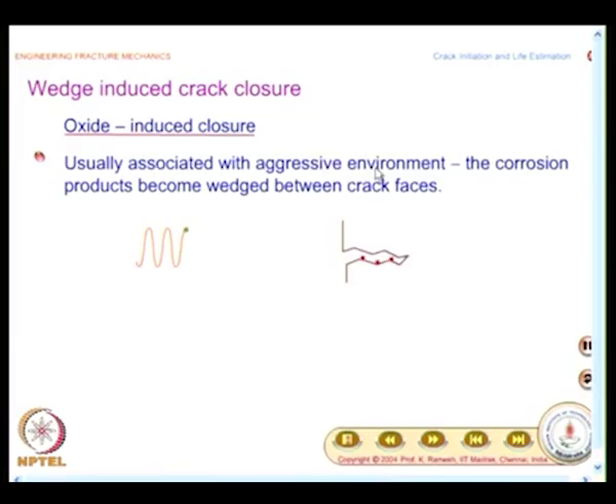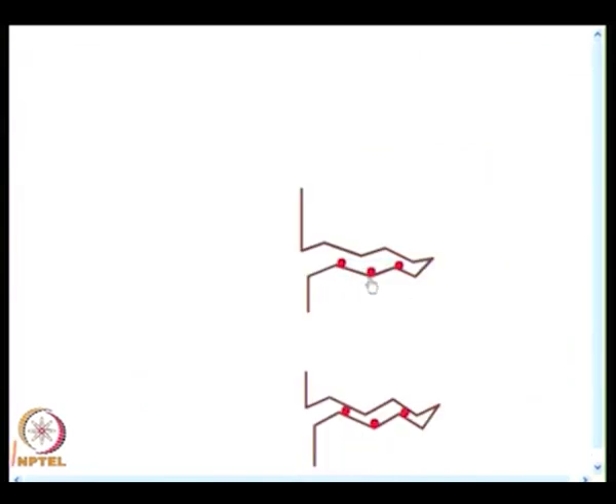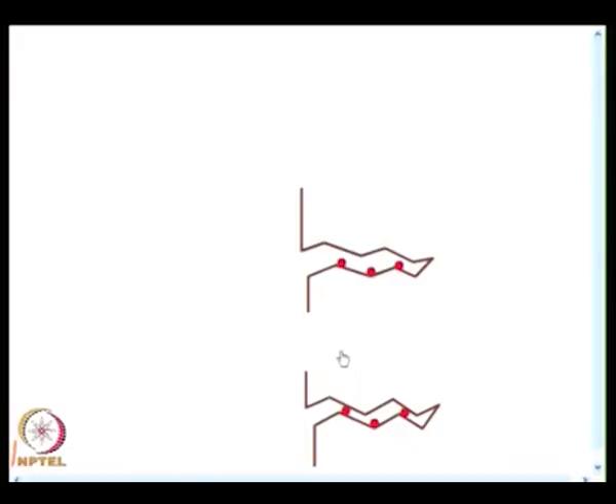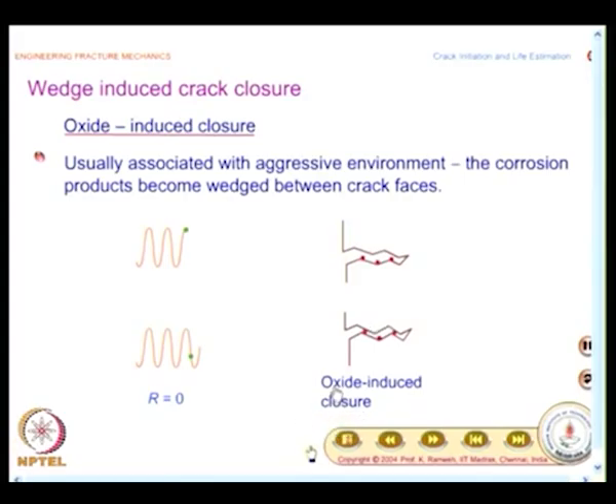usually associated with aggressive environment. The corrosion products become wedged between crack faces, that is what is shown here. I can show it a little bigger. Because of the corrosive action you have corrosion product shown, and when the load is reduced, because of the corrosion products it appears as if the crack is closed. It has a similar effect of crack closure, and this is called oxide induced closure. So, this is observed in aggressive environment.